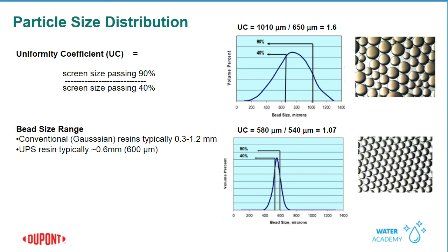And if you look at the bead size range going across, you'll see that in the top example, the Gaussian, we have particles present in a very broad range, and the typical range for that is around 300 microns to over 1,000 microns. So you'll see small and large particles present at significant volume percents there. Whereas if you look at the uniform particle size range on the bottom, that is much narrower. And the typical range for that is around 600 microns plus or minus 50.